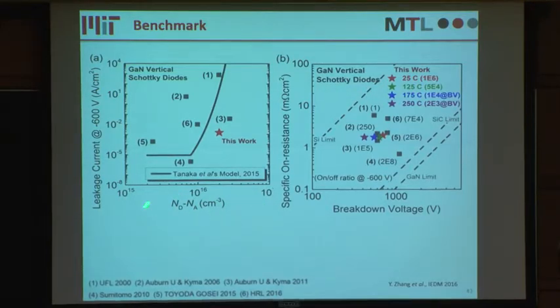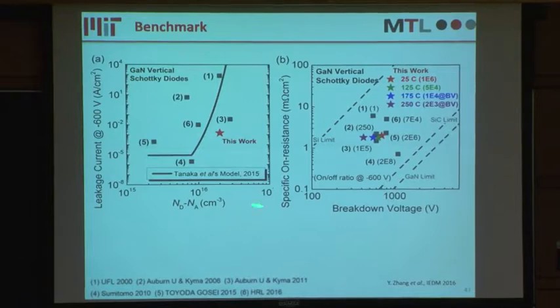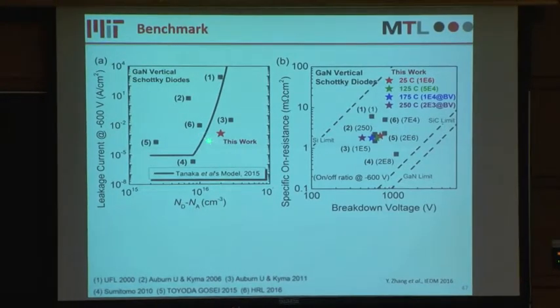If the net donor concentration in the drift region is higher than 10 to the 16, the leakage current will shoot up very quickly. Unfortunately, the wafer for our devices has a relatively high donor concentration, 2 times 10 to the 16.